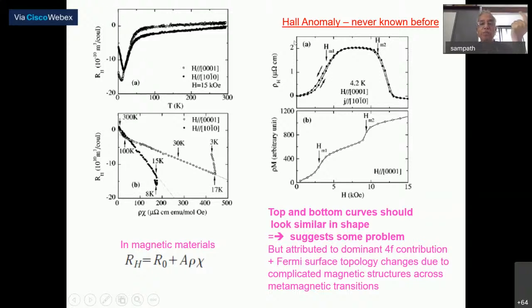I mean, people who do Hall measurements will know that you don't expect 2 micro-ohm centimeter in this magnetic order. Normally, nano-ohm centimeter, so very, very huge. We raised the question, values are large. There's a maximum, and not only that, the law which is mentioned is breaking down here. The Hall resistivity is a function of the normal resistivity and the anomalous resistivity due to magnetism. And this law is breaking down. As per the law, we plot rho_m as a function of H, and rho_H as a function of H. Both curves should look similar. They are not looking similar. We claim there is a very interesting magnetic structure in this material.